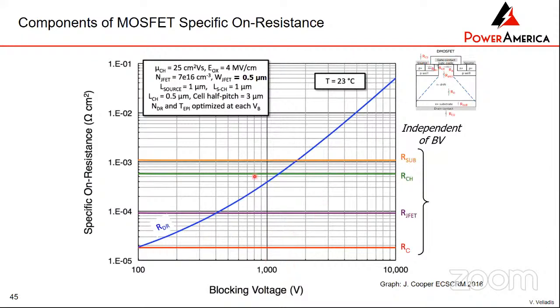So if you want to make a 1000 volt device, you can see that the highest contribution to the resistance comes from the substrate. The second highest contribution is the channel, and then you have the drift layer, which is the thickness of this layer right here. And then you got the JFET region and the contact region. However, if you make a 10,000 volt device, you can see because this layer has to be very thick for 10,000 volts, that the biggest contribution comes from that thick drift layer, and then the substrate and the channel are lower.